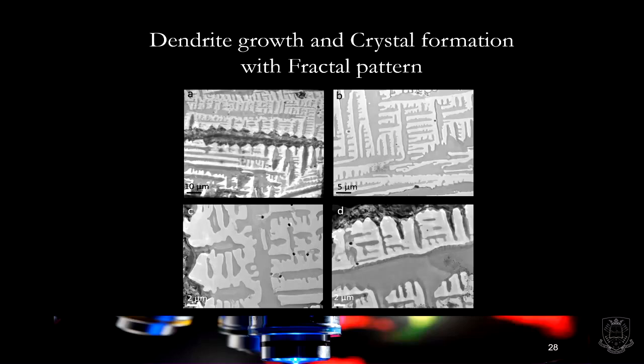Then I saw this as an example, as one of my first tries with transmission electron microscopy. What you see here is this kind of dendrite growth, almost like we saw in the snowflake. Then we have this hexagon growing into arms. At least this is always how a snowflake looks, but you know all snowflakes look different. But we always have these six arms. So the dendrites, the arms that are growing out, mirror the crystal structure that you have. The water molecules form this hexagon. We have the angle there, and it changes a little bit when it crystallizes. That's why it becomes a hexagon when they go together.